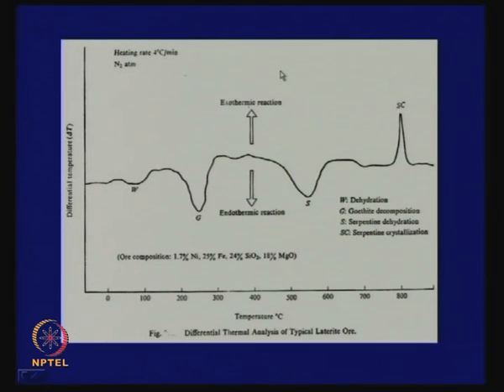So, we can say that in ores which are lateritic, all pyrometallurgical operations must be below 800 degrees to ensure that nickel is not locked up in a serpentine recrystallized phase. However, limonitic iron ores, which have more iron content, 40 to 50% Fe, would not have the serpentine peaks, but a serpentinic ore with a low iron content, 8 to 10% Fe, will not have the goethite dehydration peak because of the lack of goethite mineral in the ore.